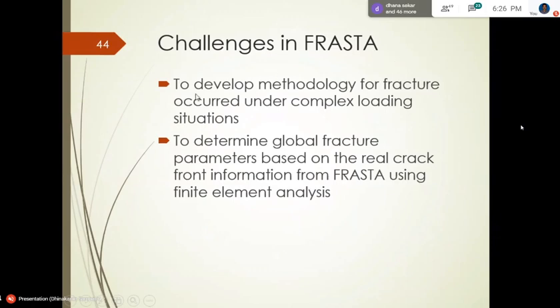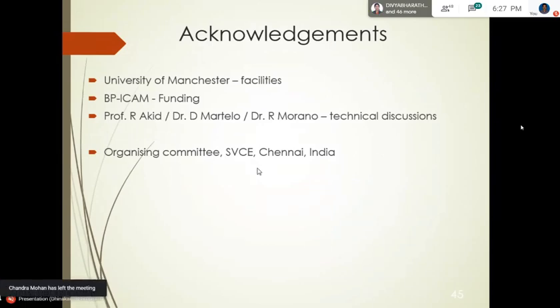Challenges. In FRASTA, we had done this simulation using uniaxial displacement. What if the surfaces undergo torsion, a combination of bending and torsion and so on? That's a scope for developing a methodology to do that, and to implement FRASTA for those kinds of situations. Secondly, as I showed, crack fronts are very easily obtained from the fracture area projection plot. We found local fracture toughness. Can we use that crack front and use finite element analysis to determine global fracture parameters like K1C, J1C, CTOD, critical CTOD? So that's another challenge, for someone interested. I think I took a lot of time.